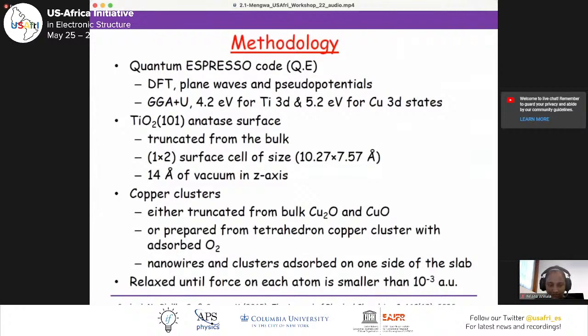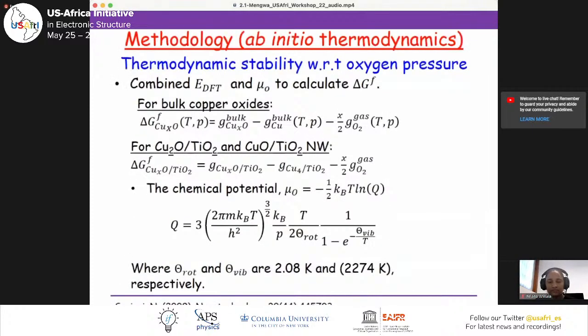We employed the Quantum ESPRESSO code, which utilizes DFT with plane waves and pseudopotentials. The calculations were carried out with GGA plus U of 4.2 eV for Ti 3d and 5.2 eV for Cu 3d states. The TiO2 101 surface is truncated from the bulk. It has a vacuum width of 14 angstroms. The copper clusters are calculated from the bulk copper oxides, or they are prepared from the tetrahedron copper cluster with the adsorbed oxygen molecule. The nanowires and clusters are adsorbed on one side of the slab and relaxed until the force on each atom is smaller than 10 raised to the negative 3 atomic units.